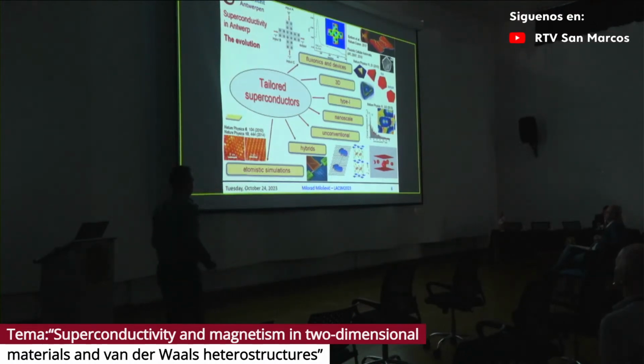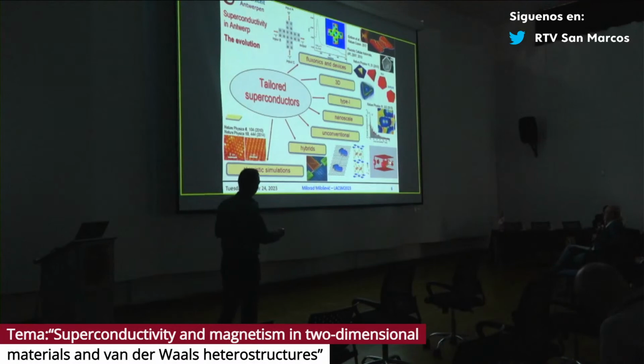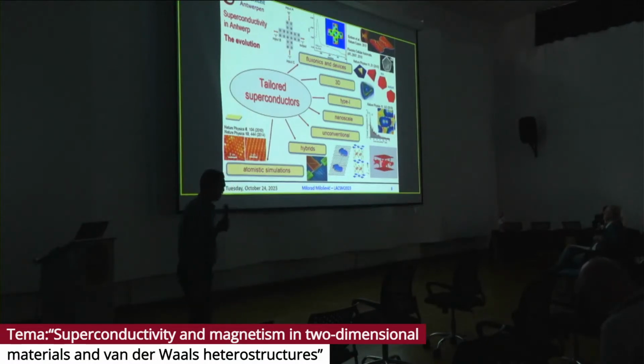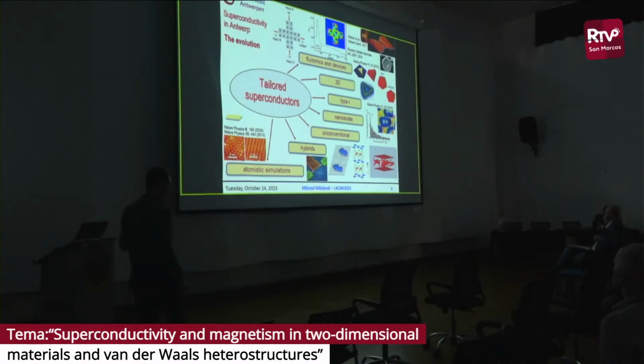Of course, there is also unconventional superconductivity. This is an example of a ferromagnetic superconductor. I think it's europium-based. So these are ferromagnetic domains inside the superconductor, and they give rise to these vortex loops and this vortex liquid that, under the influence of current and field, present very unusual phenomena.